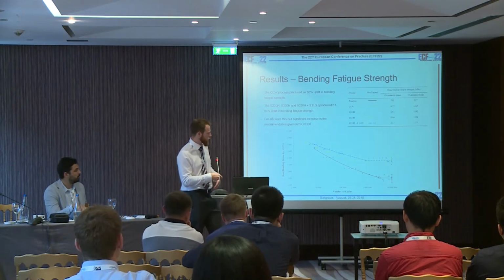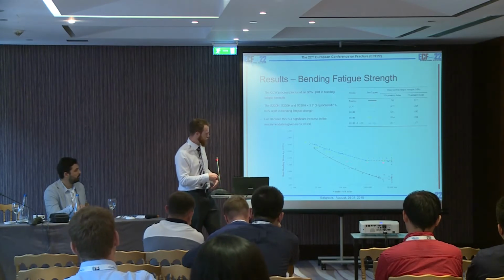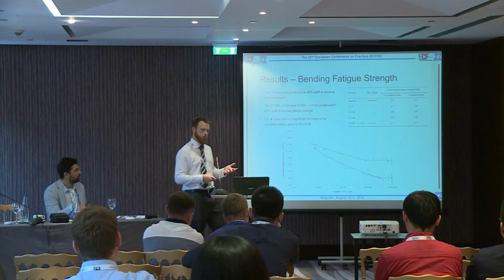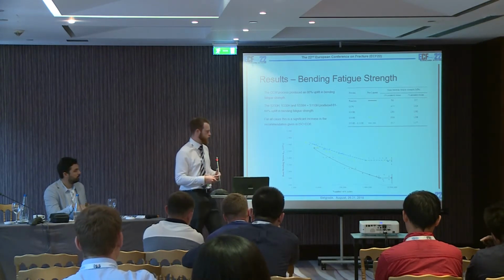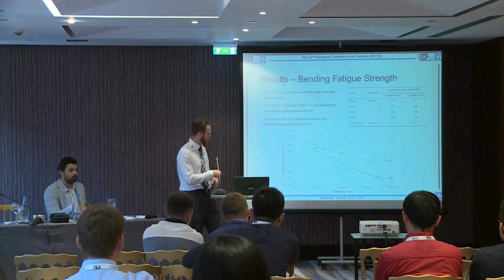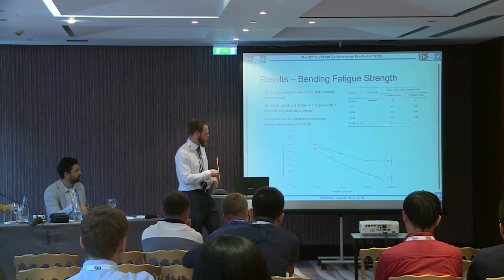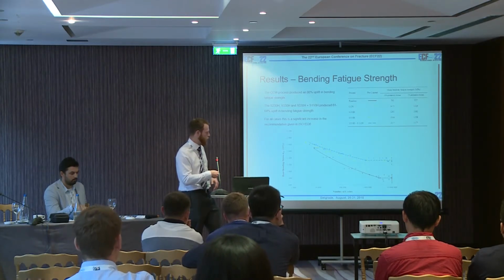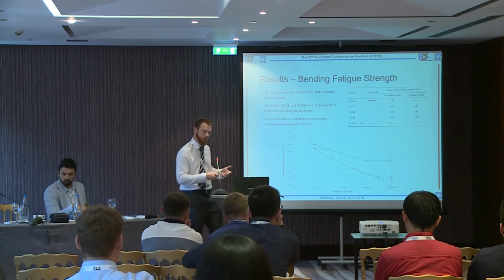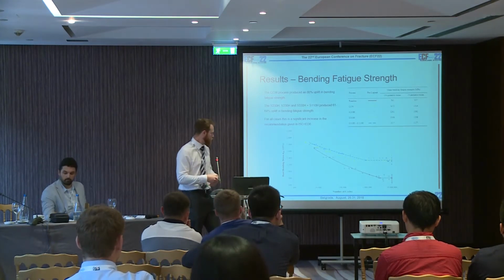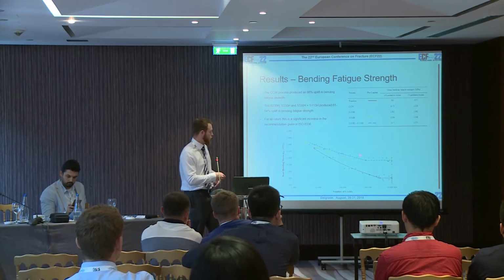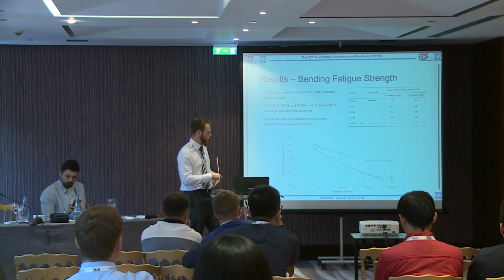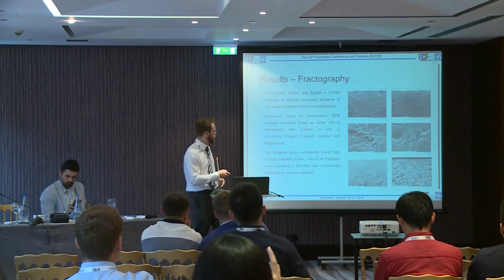The other three processes actually produced very similar results, despite the fact that we saw slightly different residual stress profiles. So they were between 61 and 64% uplift in bending fatigue strength. I think again here, there is a reflection in the fact that there is some difference in the duplex process. So in the finite life region, we do see some small increase in life for any given root bending strength, stress, sorry. So overall, the condition cut wire process gave us the greatest uplift.